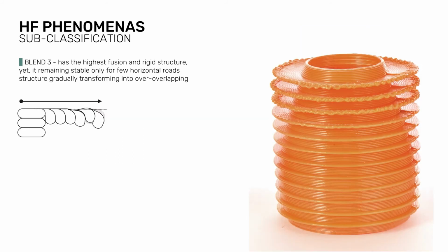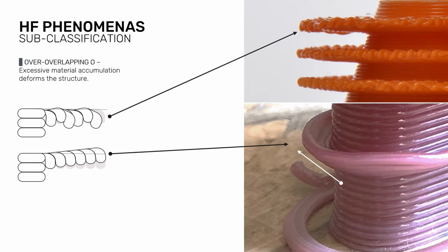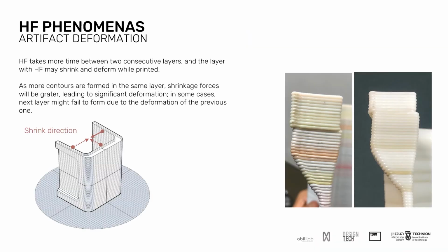Blend 3 has the highest fusion and rigid structure, yet it remains stable only for a few horizontal rods. Then, due to material overaccumulation, extruded material pushes the horizontal structure in a random pattern. Overlap is observed in 2 different forms. When the horizontal structure is solidified, a random pattern appears. Yet, when it's still soft, this structure bends in the up direction.